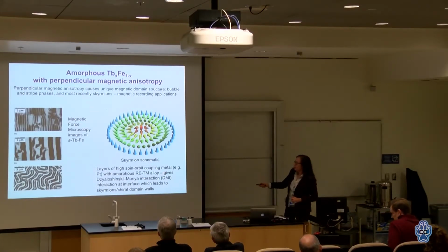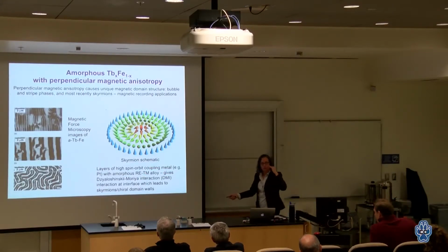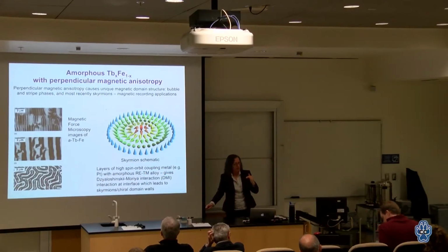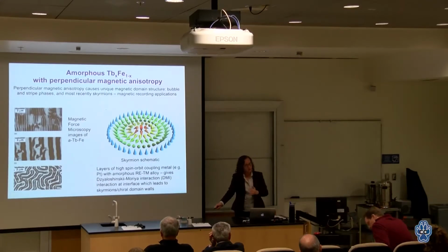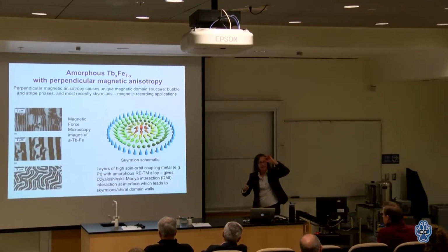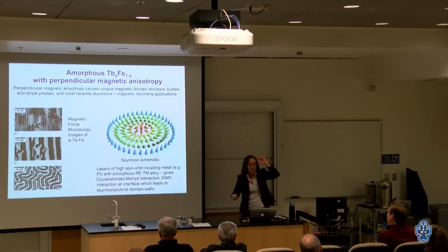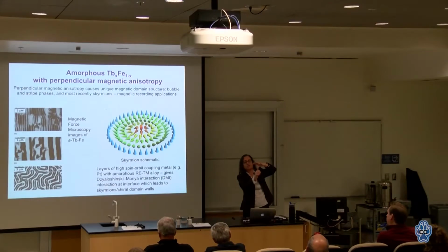If you take amorphous terbium iron and you layer it with a material like platinum, a heavy element with lots of spin orbit coupling, it turns out that interface has a unique property. The fact that I have terbiums and irons pointing this way, and then platinum with its strong spin orbit coupling, which has a sign to it, makes the terbium irons not just want to point parallel to each other, but there's actually a cross product. And that cross product gives it a left-right chirality.